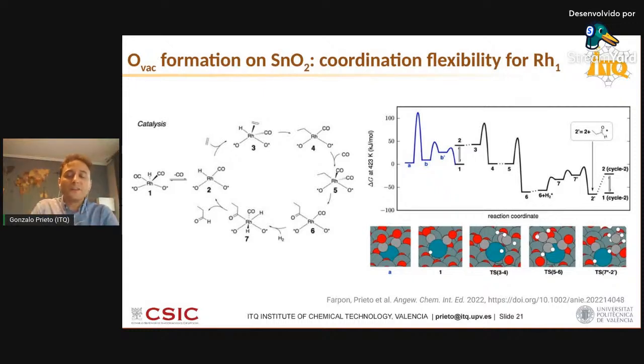And actually, part of this lattice oxygen coordinates to the rhodium atom to some extent. So it is the rhodium atom which is also losing ligands, and has an average coordination number of around 4 under reaction conditions. That is an experimental coordination number that we interpreted this way. On the left-hand side, we were proposing a resting type of active center where rhodium has effectively a coordination number of four: two lattice oxygens, only two, on the tin oxide support, plus two CO molecules.